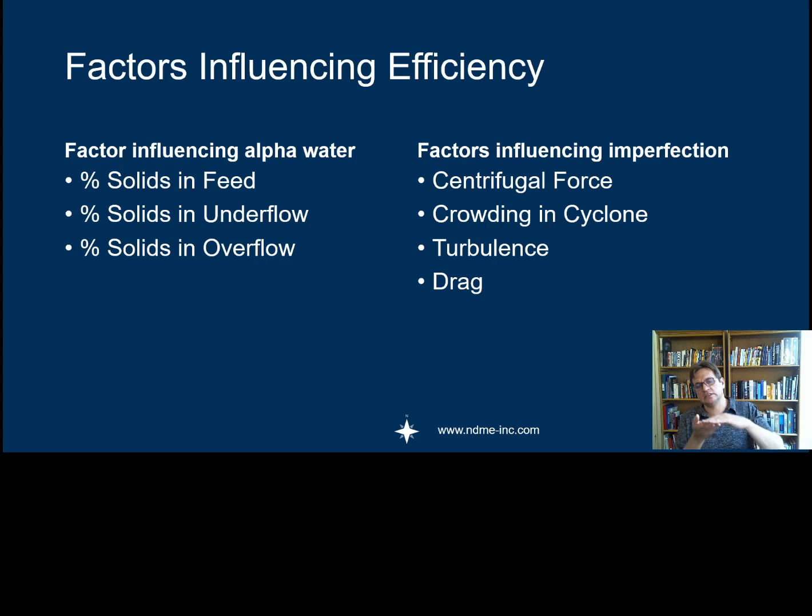These are also functions of other things that you can control, i.e. remember that I said a cyclone is made of various components. If you were able to make the cyclone longer, you create residence time in the cyclone, so it is a contributor to more effective separation. But having said that, what I've found, even between different cyclone suppliers and cyclones, and we argue too often as metallurgists till the cows come home, is you are not going to get that separation efficiency curve moving so much in terms of the sharpness of cut.